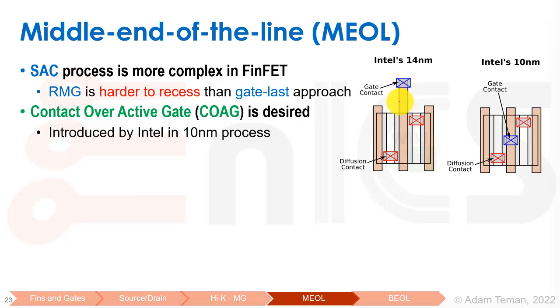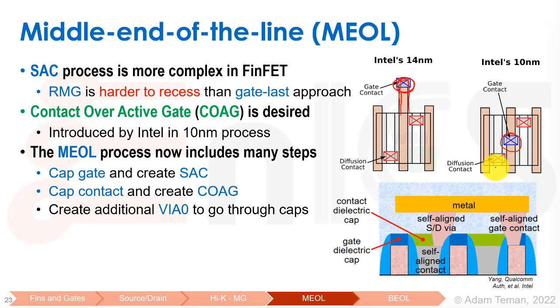So what that is, as we said, we used to pull out our gate layer, our poly over here, and then contact it somewhere outside the cell, but that's really wasteful. Instead of that, what Intel wanted to do at 10 nanometers, and did, is to put the gate contact right on the channel itself, and therefore save a lot of area. And this they did. It cost them a lot. In fact, one of the biggest problems for Intel ramping up the 10 nanometer process and getting to higher yield is all this middle end of the line, which was really problematic, and specifically this contact over active gate.